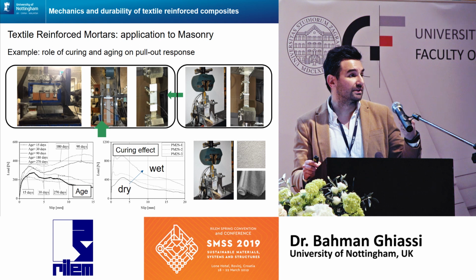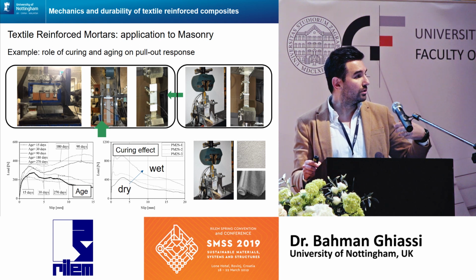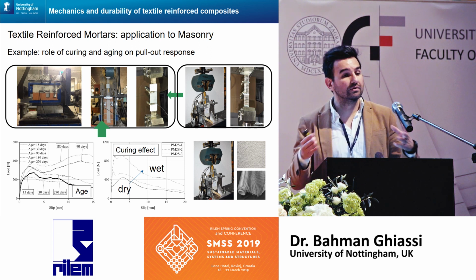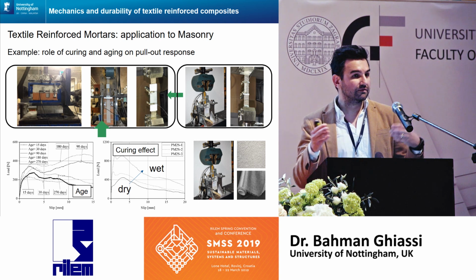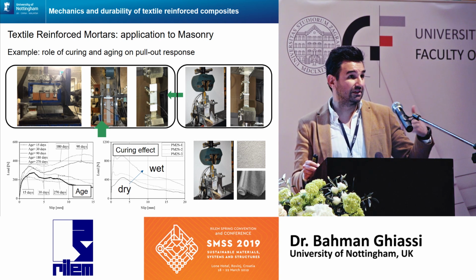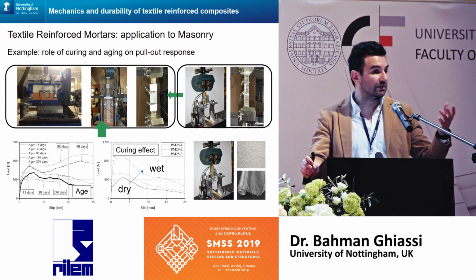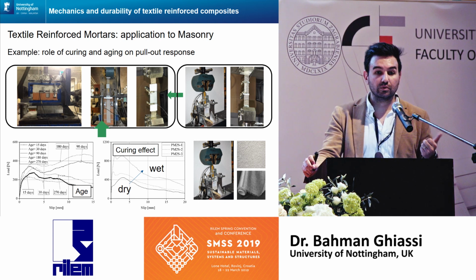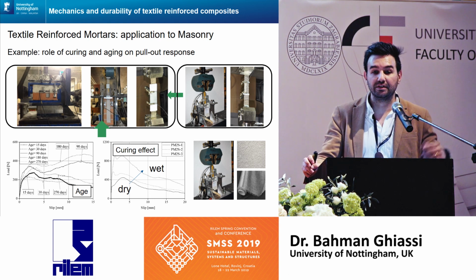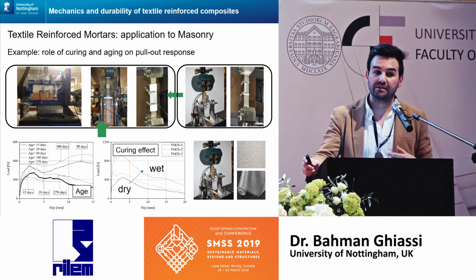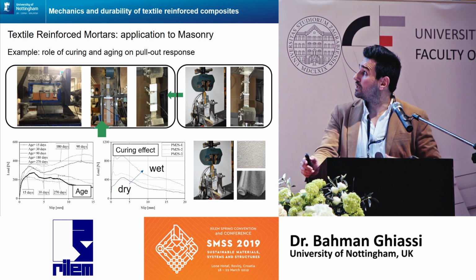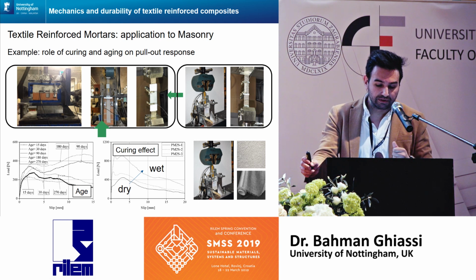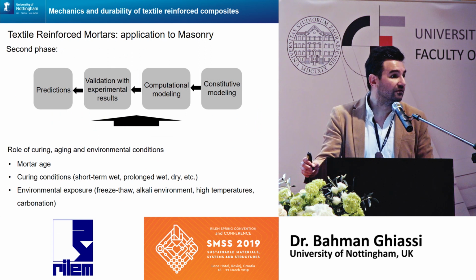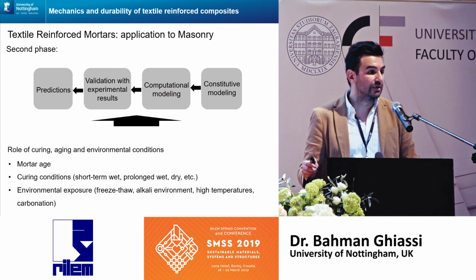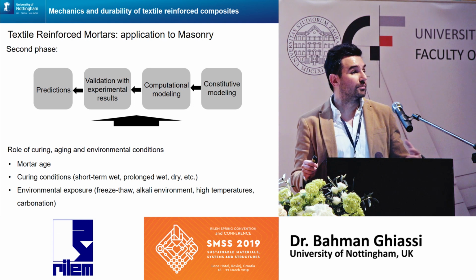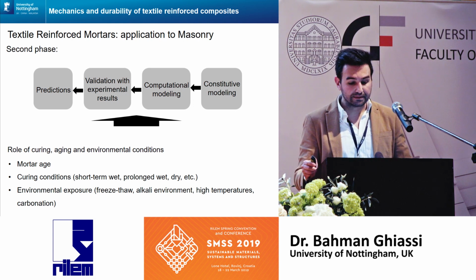If we cure the mortar in a dry environment, or in a short wet environment, or in a prolonged wet environment, which is very sensitive in real applications, because in real applications you cannot really control the curing conditions. So what happens if you are applying this material on a dry day or on a wet day, and how that affects the performance at the structural level is important. Or for environmental conditions, we are investigating the freeze-thaw behavior, alkali environment, high temperatures, or even carbonation effects on the performance of these systems through all the scales.